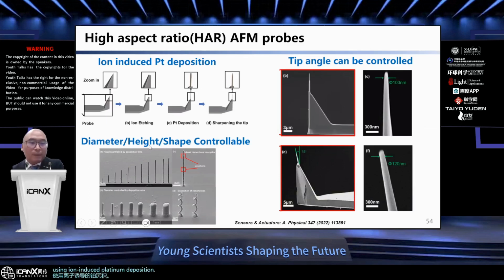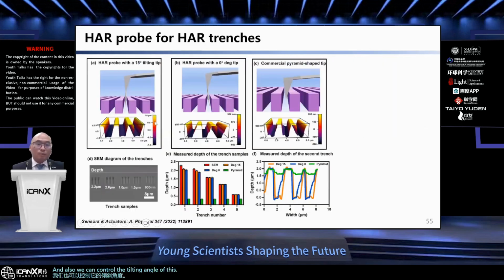So the last one is a high aspect ratio AFM probe using ion-induced platinum deposition. We can control the diameter, height, shape, and also the tilting angle of this tip. Okay, so then we found that for measuring high aspect ratio trenches, if you're using a conventional sharp tip, you cannot touch the bottom of the sample.